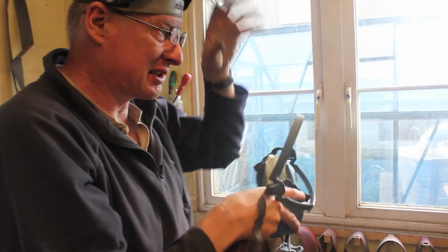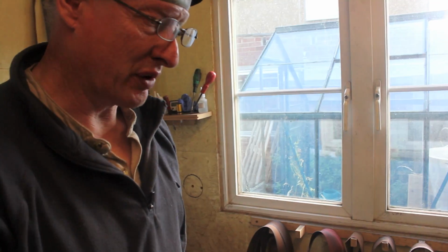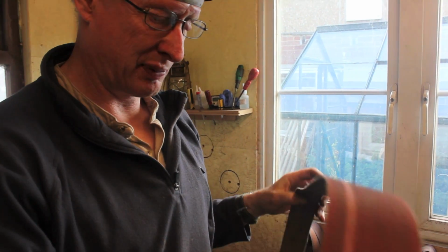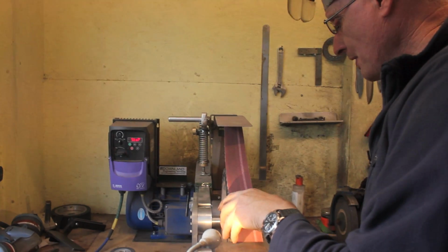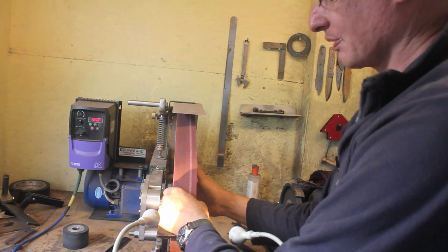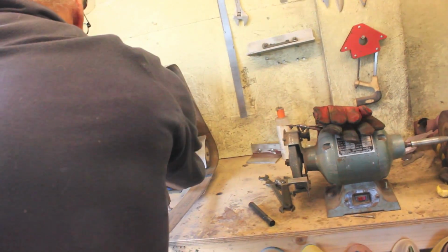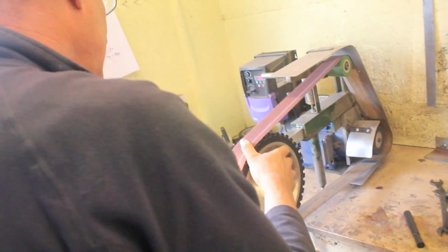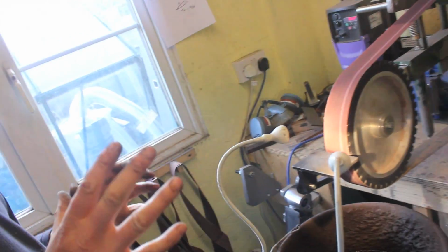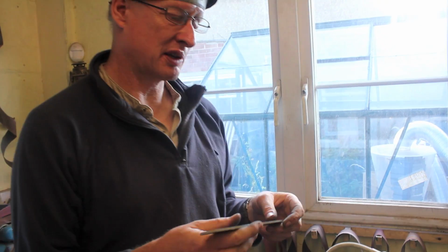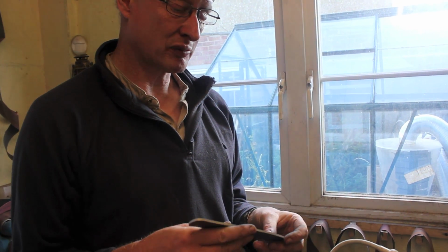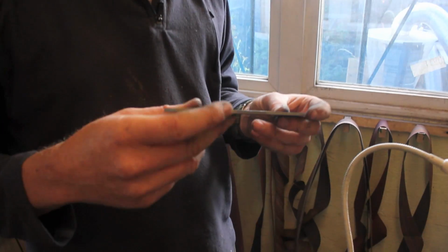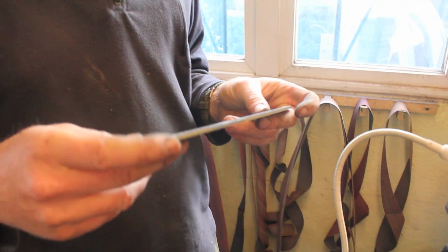There's no great necessity to keep the knife from getting hot at this stage, but I always do dunk it in water to keep it cool when I'm drilling or when I'm grinding, because I find that by keeping things cool in the early shaping stages, you minimise the chance of a warp during the quench, the heat treating. Because when you heat up steel, you're putting hidden stresses into the steel. And it's those stresses which manifest themselves afterwards when you come to quench it, and you suddenly get a blade that warps. I just found that by keeping things as cool as you can during the shaping and drilling processes, it doesn't seem to warp so readily.